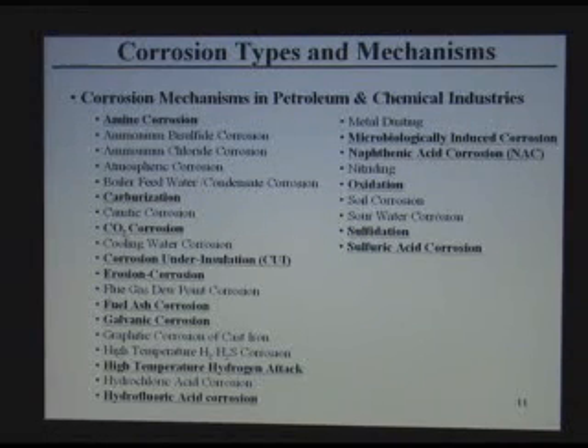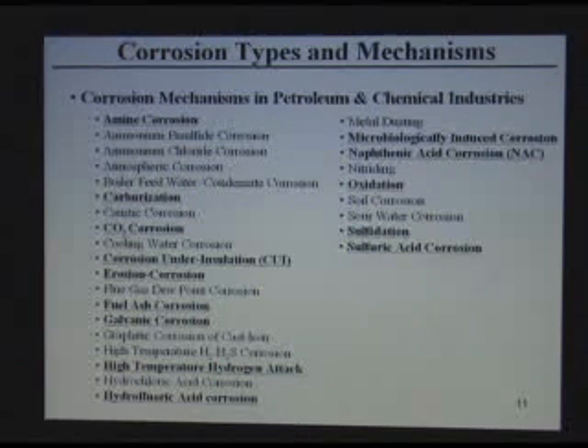High temperature hydrogen attack is when you have high temperature hydrogen at high partial pressure, hydrogen can react with the carbon in the steel and can cause cracking of the material. Hydrochloric acid, of course, HCl is a very corrosive acid and can corrode. The same for hydrofluoric acid. And then metal dusting, something you don't see except in hydrogen reformers and ammonia plants. It is some kind of carburization, but a slightly different